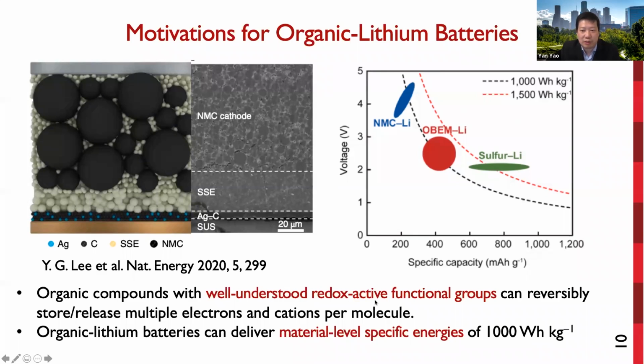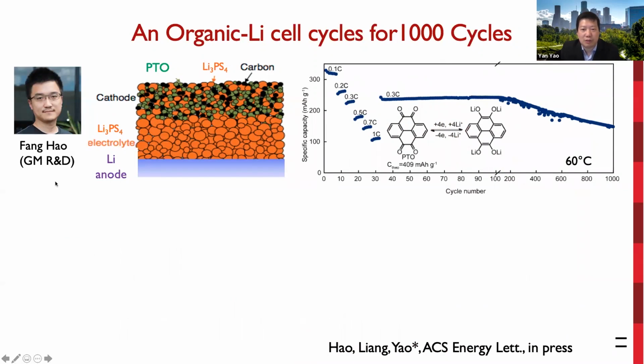So organic lithium batteries have the potential to deliver material-level specific energy over 1,000 watt-hour per kg, placing them in the same category as NMC-lithium and lithium-sulfur batteries. Fang Hao was the first graduate student who worked on this project. He's now at the GM R&D Center. The organic we used in this research is called PTO, and each molecule undergoes 4-electron reduction along with 4 lithium-ion insertion into the molecular crystals, coordinating with oxygen atoms. This reaction corresponds to a theoretical capacity of 409 milliamp hour per gram.